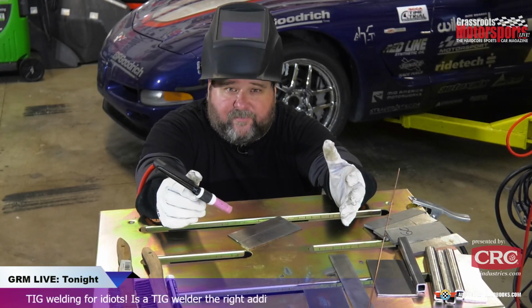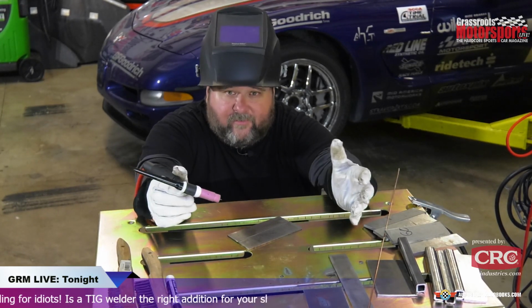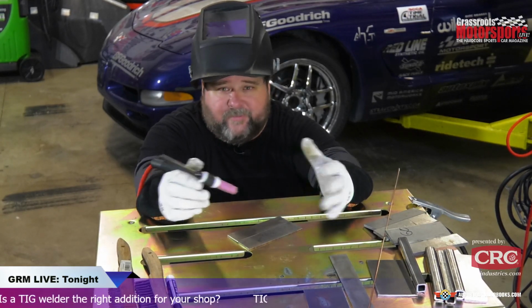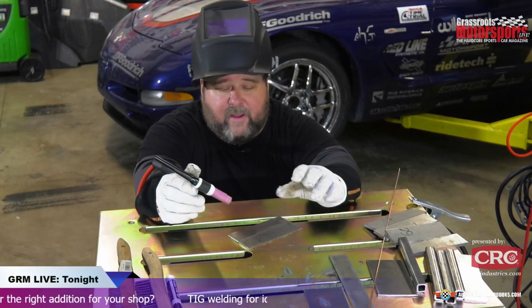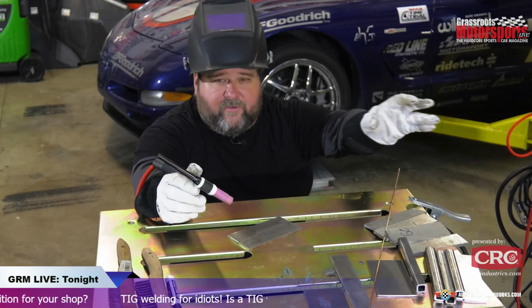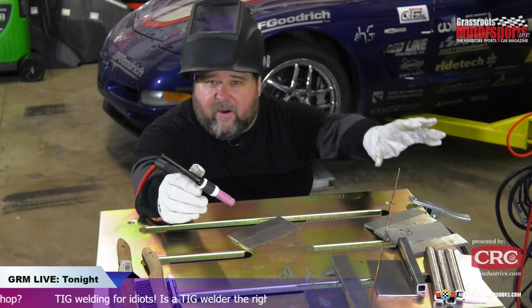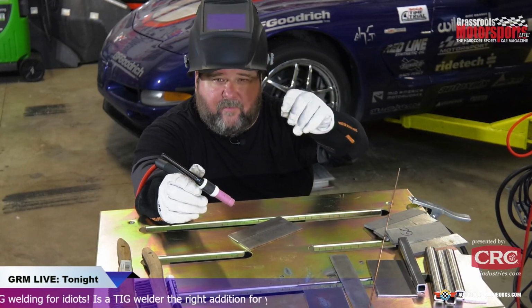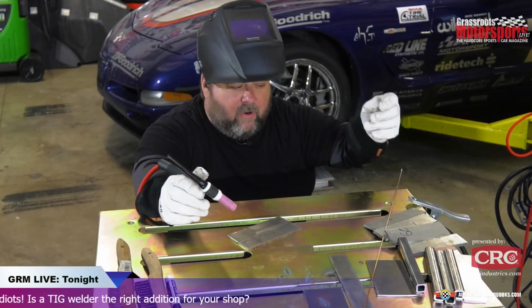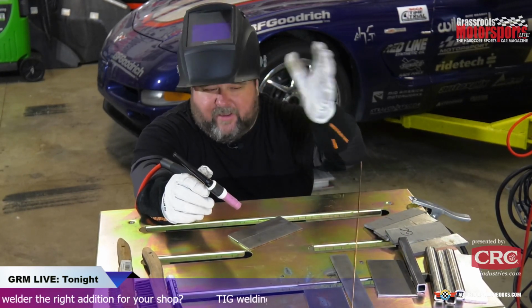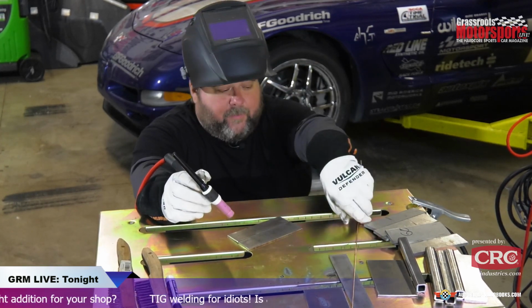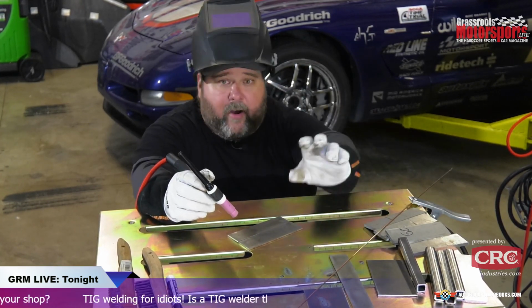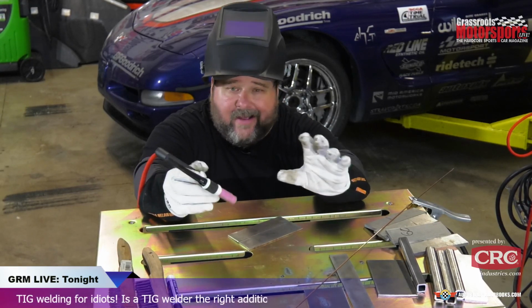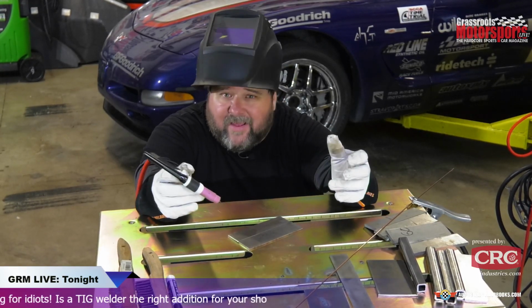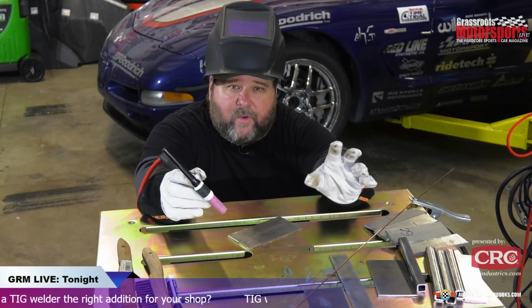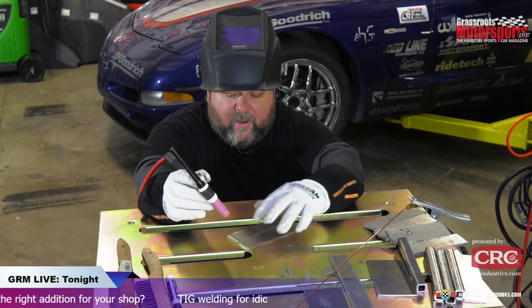You get that tungsten electrode into your puddle, your tungsten is essentially at that point done until you grind it again. You're going to have stray arcs going all over the place. You're going to have secondary arcs trying to start, because that electricity is going to have different paths to ground, and everything goes to hell at that point. So keep that tungsten out of the puddle, but keep it close. That's why it's a very delicate procedure. You want 3 or 4 millimeters between the end of that arc and the top of your puddle.